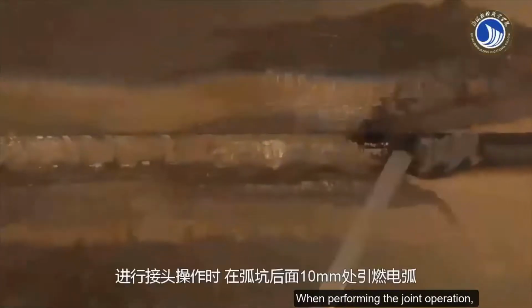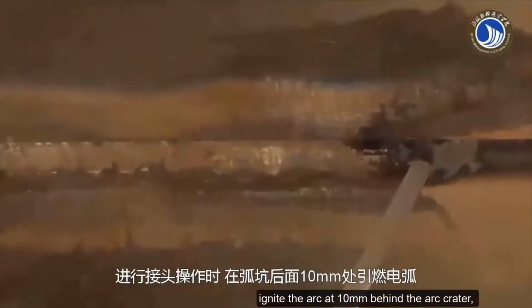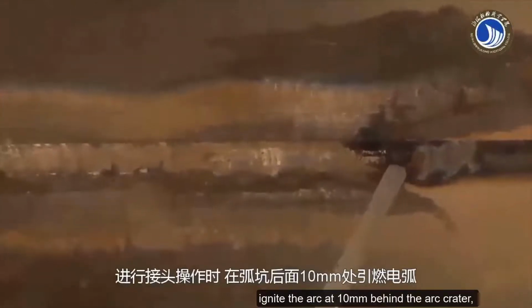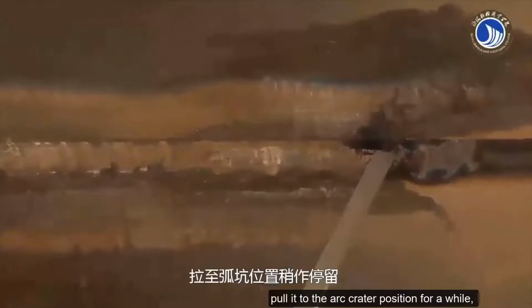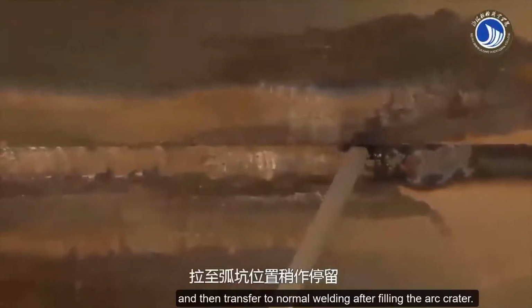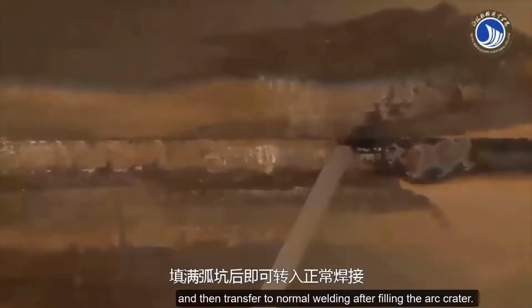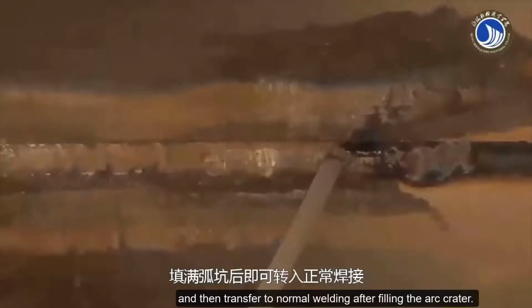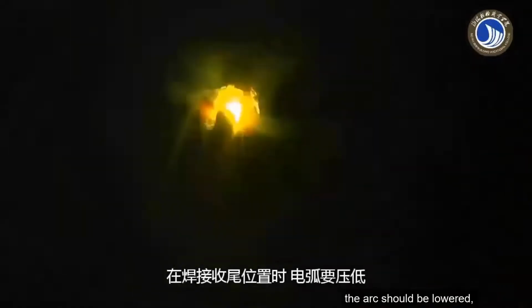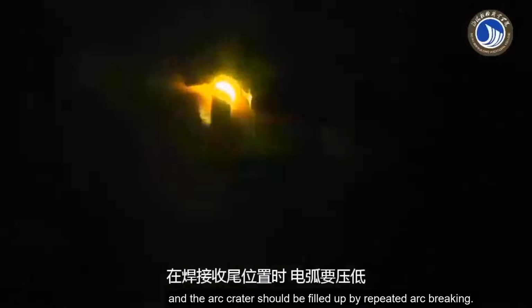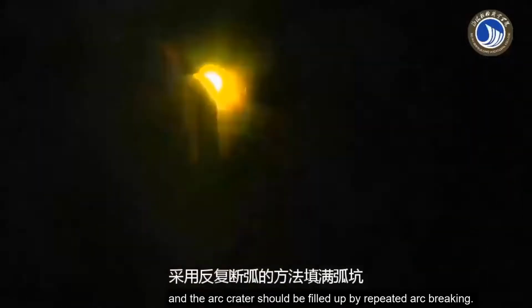When performing the joint operation, ignite the arc 10 mm behind the arc crater, pull it to the arc crater position for a while, and then transfer to normal welding after filling the arc crater. At the welding tail position, the arc should be lowered, and the arc crater should be filled up by repeated arc breaking.